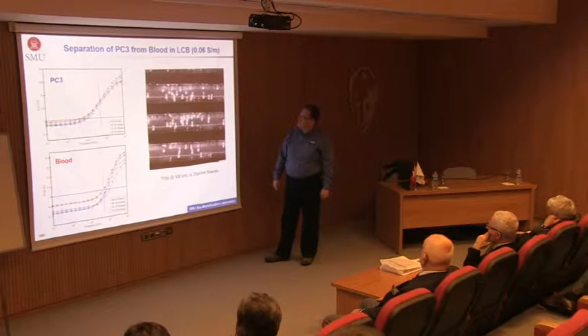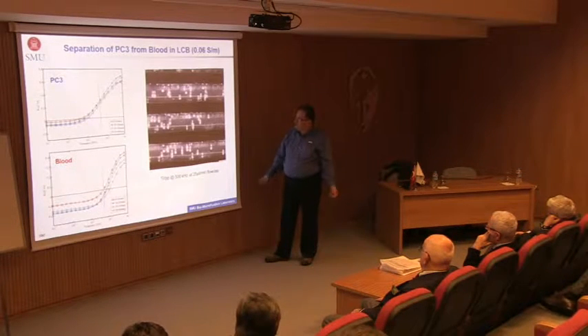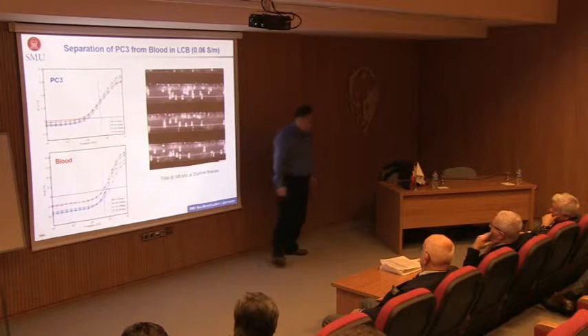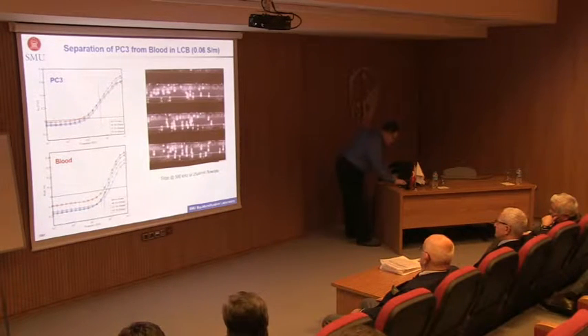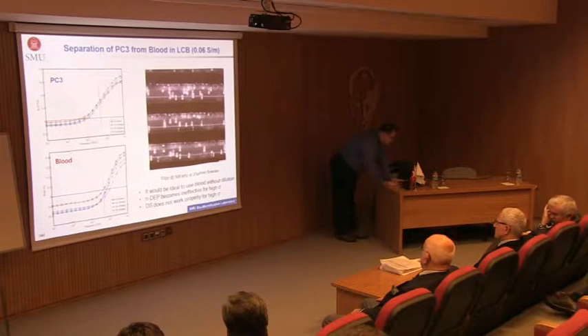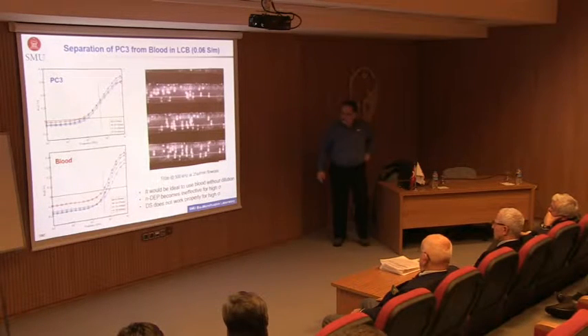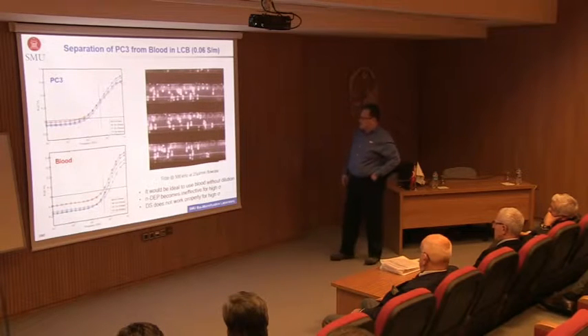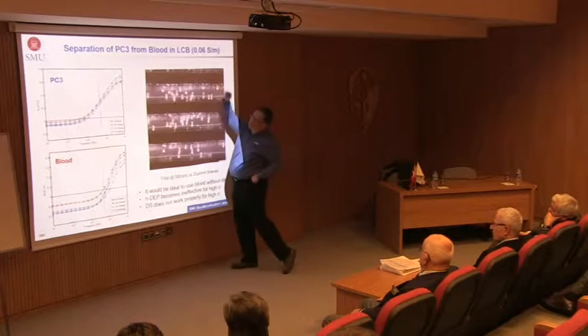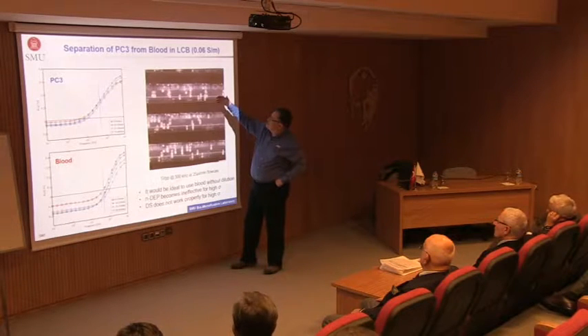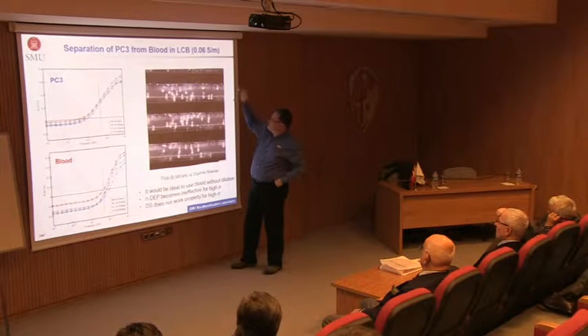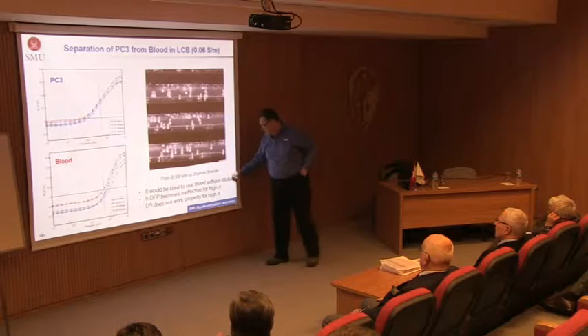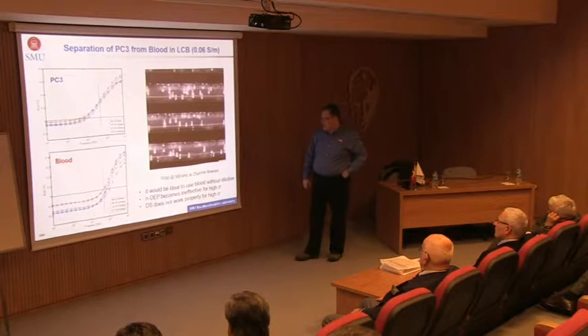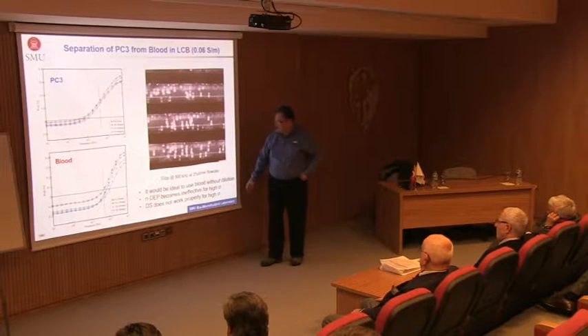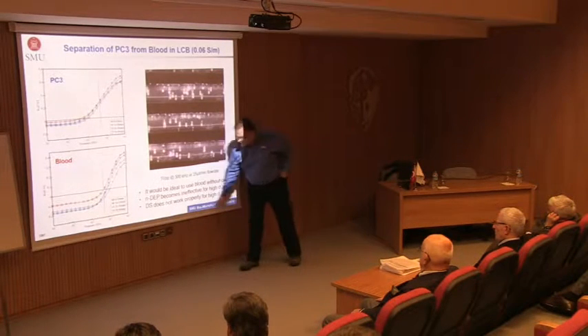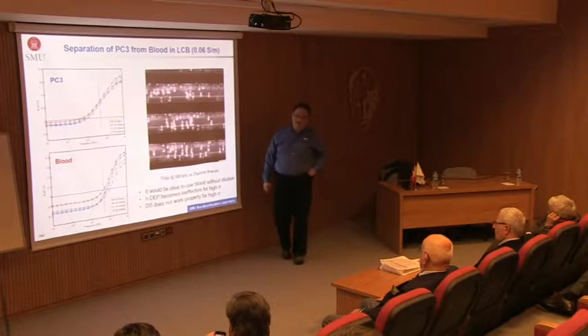And you can actually see that this really works. Of course, there might be some stuck white blood cells in there as well, but this is for us to discover later on. So overall, though, there's a caveat, is that we have to use 0.06 Siemens per meter, but the blood is 1.5 Siemens per meter. That means there has been dilution in this. It would be nice to do this without dilution. But then negative DEP becomes ineffective at high conductivities, and dielectric spectroscopy does not work very well either.